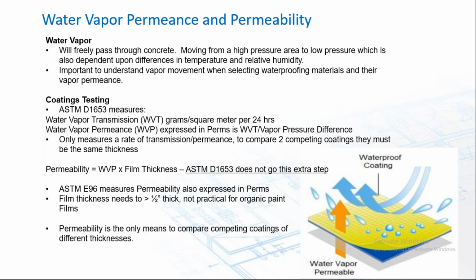Permeability is the only means to compare competing coatings at different thicknesses. So pay attention when you're looking at the test results for ASTM D1653. Manufacturers should provide you with the perms and the film thickness at which it was tested, because it is a linear relationship. Twice the thickness is half the permeability. So you need to take that into account.